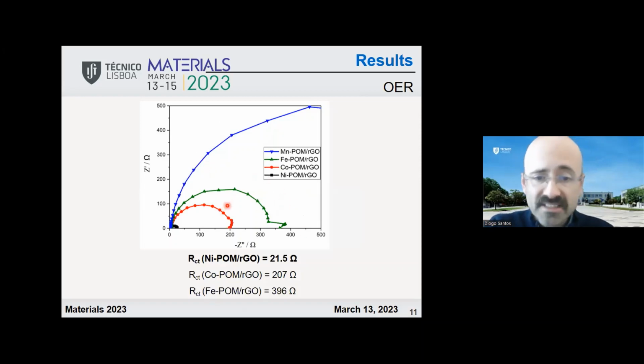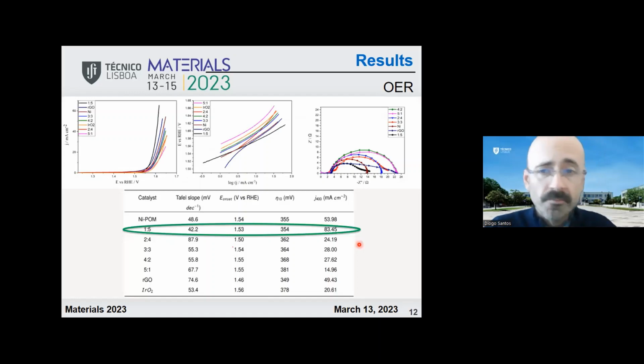So this shows again what I was focusing on, and here we see clearly the charge transfer resistance for the nickel POM was much lower than for the other materials, showing the good activity of the nickel POM.